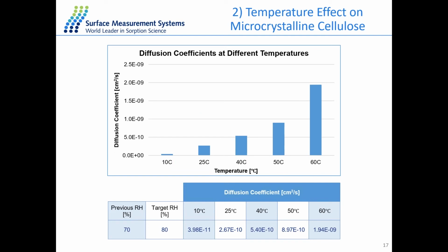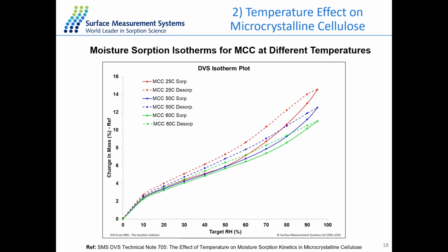And the diffusion constant is calculated with the average particle size of the microcellulose material, which is about 50 micrometers. And this diffusion constant also shows a trend of increasing with increasing temperature. And another observation is about the hysteresis gap between the sorption and desorption isotherm. So the red line is for the 25-degree run, the blue line is for the 50-degree run, and the green line is for the 60-degree run.